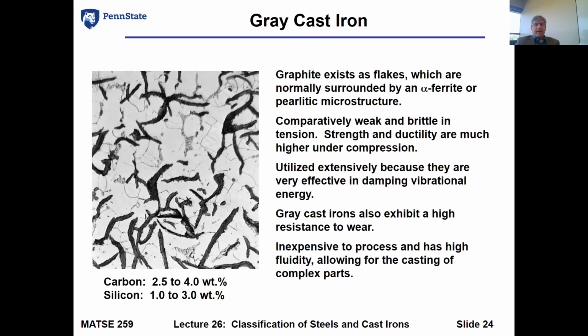If we look at gray cast iron, it is probably the oldest of the cast irons that we would typically use. It tends to be inexpensive. It's easily cast, which is where this high fluidity comes in, so you can produce complex parts. It has good resistance to wear, because if we look at this microstructure, it's got 2.5 to 4 weight percent carbon, which tells you right off that it's going to be very hard. The high levels of silicon promote these graphite formations. But in gray cast irons, we can have a pearlitic or a ferritic microstructure around it. They tend to be weak and brittle in tension, but they're much better in compression, which you would tend to expect for anything that's hard. They're very effective at damping vibrations.